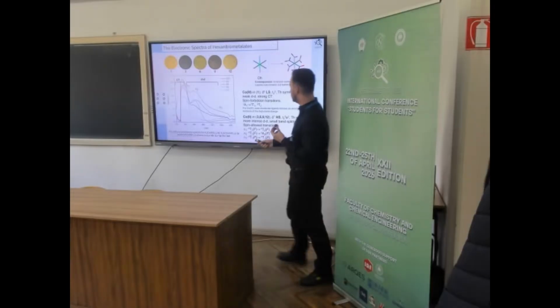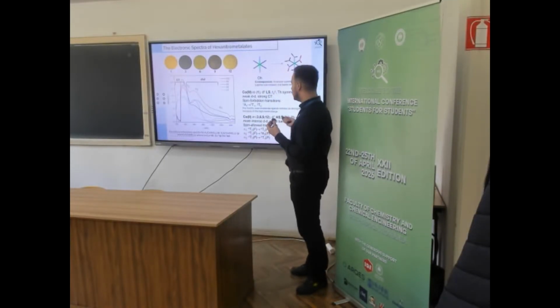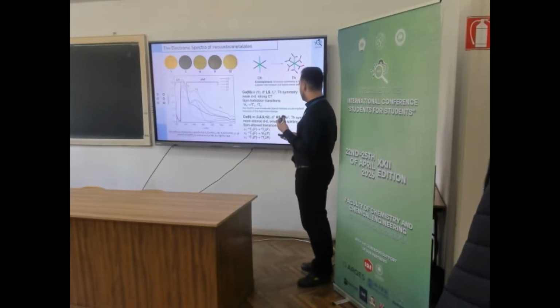The first complex we're going to look at is potassium hexanitrocobaltate, in which the cobalt is found in +3. It is found in low spin, and as you can see, the d-d transitions in the first band here are very weak because of its charge. The charge makes the splitting of the orbitals very large. NO2 basically acts as a strong field ligand, even though it's a moderate one. The transitions are not possible because the complex is low spin and there are spin-forbidden transitions.